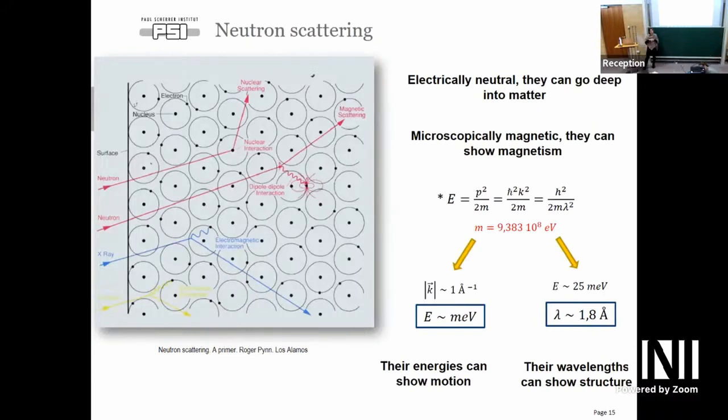There's this when you're trying to measure magnetic field with polarized neutrons. Yes, where the neutron just goes in a straight line. Yes, the polarization spectrum. But here, it interacts with the wave, let's say. Yeah, and the diffraction is influenced by it. Exactly. So you can also have new peaks in your pattern due to the magnetic peaks, right? If you have a magnetic structure, you will see that. You don't require any polarization to do that, right? It's just a new phase, let's say.